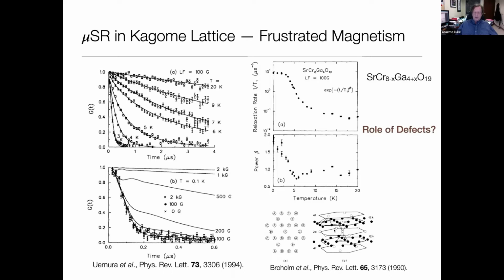that can lie on the planes in between the Kagome planes, and that may be resulting in some of the anomalous behavior. So there's been a constant search to try to make better candidate materials which have fewer possible confusing details in them to make them the best possible example. This is a very interesting material, though. It has spin dynamics which slow down. The spins remain dynamic to the lowest temperatures, but the spin dynamics are not understood in terms of how it works. So even if this is a more complicated example, it still raises a lot of questions that even now are not yet understood.